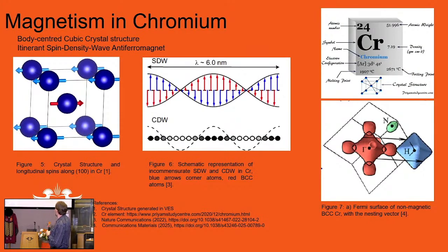And then what happens is throughout the lattice, now we've got one cube structure here, we deal in three-dimensional space. What then happens is you can form a standing wave of these spins traveling through the lattice, not necessarily a single cube. You actually have to stack nearly 21 of these in a row. Then you form this middle picture where you've got the standing wave of about 6 nanometers. It's slightly out of phase with those 21 lattices. And depending on dopants we add, you can shift that in or out of phase, of course with associated properties.